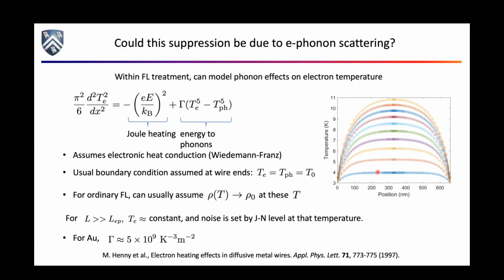Bottom line, if you do this measurement in gold, this has been done by multiple other groups, and we did it too, just to confirm. This number gamma is around 5 × 10⁹ in these SI units. Okay, so I have no intuition for this, but that's what the number is.